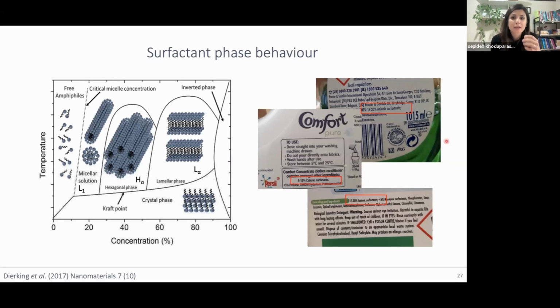So when you dilute this, and you dilute this significantly, you want to still stay in this kind of phase behavior. There's one problem with this phase, both in terms of formulation, when it's being produced and when you want to use it, is that when you reduce the temperature, there are different phase transitions going from this micellar phase to different phases. So if you increase concentration or cool down around this zone, you go to these liquid crystal phases.